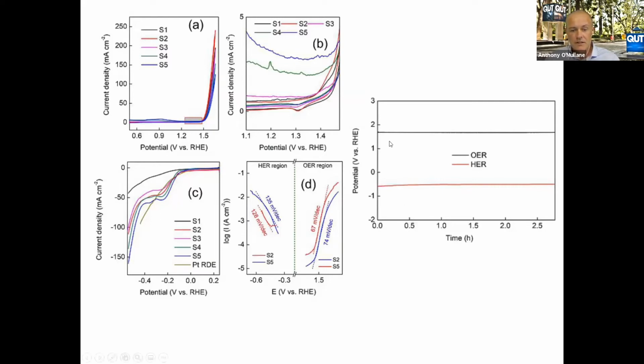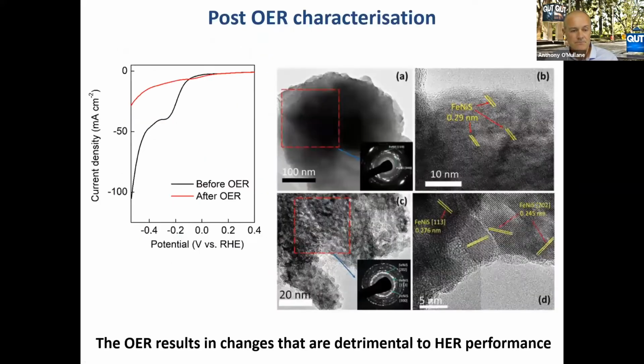If we look at the oxygen evolution voltage and the hydrogen evolution voltage, you can see that for a 2-electrode cell, we don't have to operate it at too high a voltage to get overall water splitting. We can also see that the Tafel slopes are quite reasonable as well for both of these particular reactions.